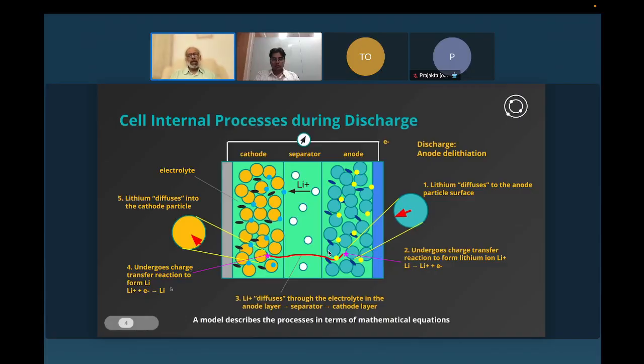Now this lithium migrates into the cathode particle, just the opposite of what it did with the anode. And as it moves inside, it makes room for the trailing Li ions and the Li to come and diffuse into the particle. So this is the sequence of events that happens when we discharge a cell. What I'm not showing here is also the gradient that's set up by the potential or the voltage gradient, and that also drives a similar transport process, as shown here.